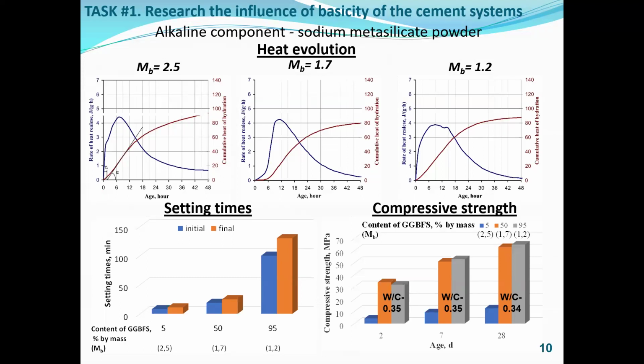With increasing the slag content from 5 up to 95%, the compressive strength of the alkali-activated cement systems at an age of 2 days increased from 4 up to 34 MPa. At later ages, with increasing the slag content, the compressive strength also increased at an age of 7 and 28 days from 9 up to 53 MPa and from 12 up to 65 MPa respectively.